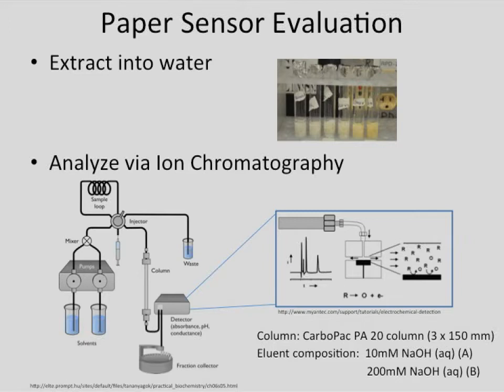So what do we do with this paper once we've aged it for the 6 days? We want to know what's no longer part of that cellulose chain—what have we broken off of it, or what have we added to it. Our main method for doing that is to just extract into water. We take some portion of the paper—0.3 grams of the 1 gram, I think it is—and then put in high purity water.